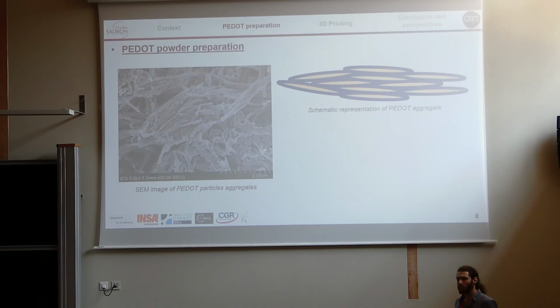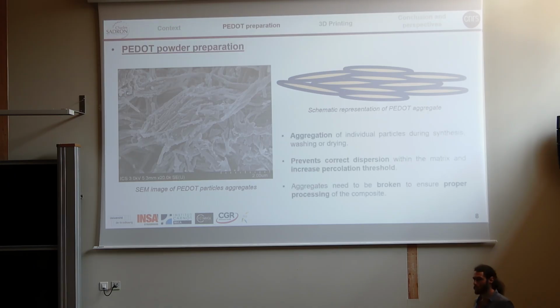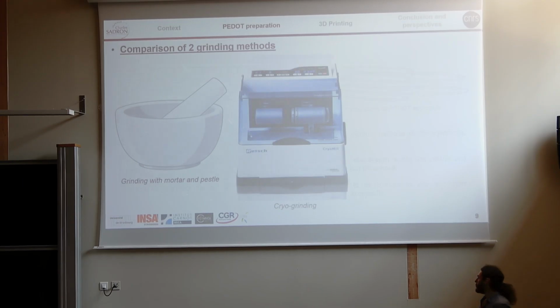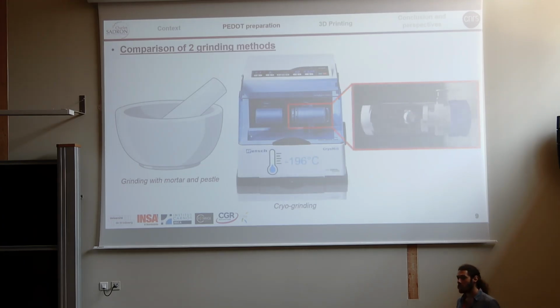So they need to be ground properly to ensure proper processing of the composite, but also a correct dispersion within the matrix. So I compared two kinds of grinding methods. The first one using just a mortar, and the second one using a cryo grinder, which will cool down the particles to make them very brittle, and thanks to the iron ball and the vibration, break them into a very fine powder.